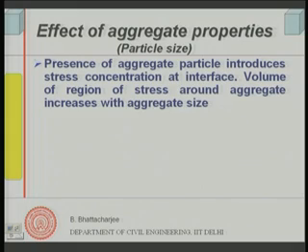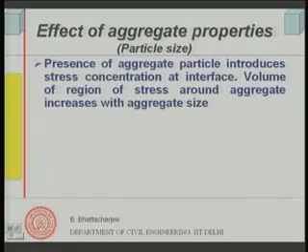aggregate, right. Now, the larger the aggregate size, the volume region of stress concentration around an aggregate particle will become larger, and the same stress has to pass through a lesser surface area, because for the same volume, larger aggregate size means lesser surface area. So, through lesser surface area, the stress concentration effect is higher. It is a non-uniformity, a discontinuity, because you are adding another material which is stronger compared to the paste, and in normal strength concrete this discontinuity tends to give you lower strength. In fact,